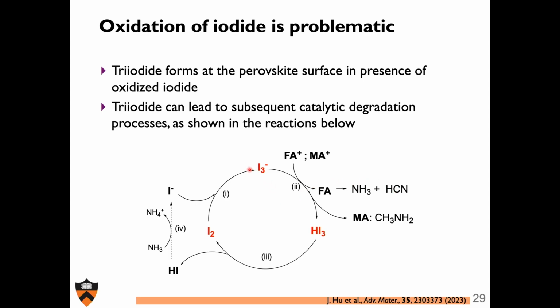If you have your halide perovskite, then at some point I will oxidize iodide. Any oxidized iodide in the presence of other lattice iodide will basically make triiodide. And unfortunately, as I'll show in the next slide, triiodide is a strong enough base to deprotonate either formamidinium or methylammonium. In the case of formamidinium, I break it down into HCN and ammonia. In the case of methylammonium, I break it down into methylamine. And the subsequent HI is the final product.